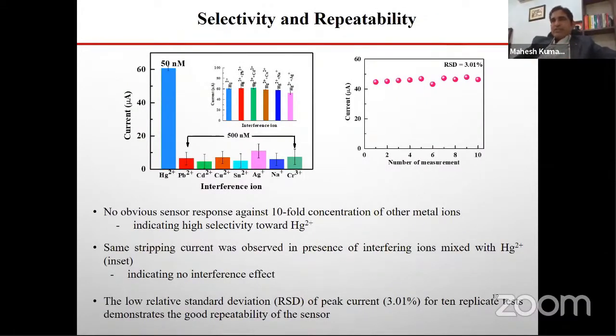Next, when making the sensor, we have to check repeatability and selectivity. Other heavy metals, for example silver and copper, are essential for our body, so how selective is it? We took around 50 nanomolar of these and tested, and found that this silver nanoparticle and graphene oxide nanocomposite is highly selective towards mercury ions. Then we did cross selectivity, and the relative standard deviation is also very low, around 3%.